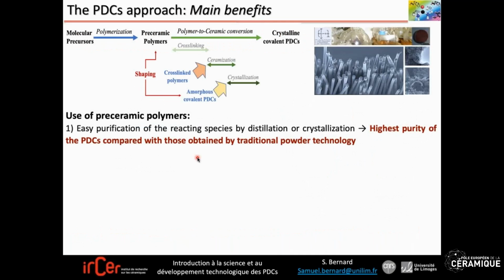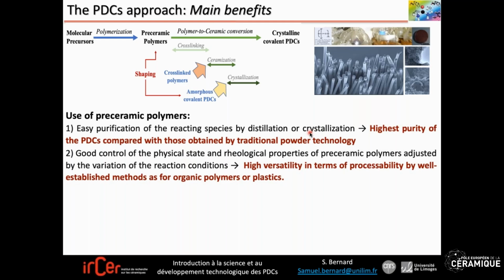So based on this discussion, we can establish some benefits of this approach. Your precursor and your polymer can be easily purified by distillation or crystallization. This means that the final materials will be highly pure. So it means you will control the stoichiometry at the polymer level. You have a good control of the physical state of your polymer, therefore you can tailor the rheological properties of your polymer just by changing the reaction conditions. So it means you have a high versatility in terms of processability to be shaped using established methods. As for organic polymers or plastics, as I mentioned previously, you can spin, you can coat your polymer, you can press your polymer, or use injection molding.